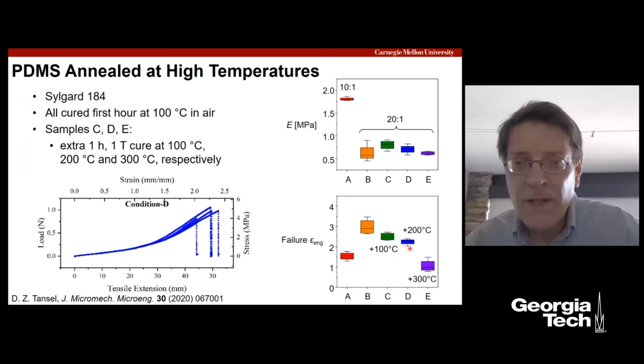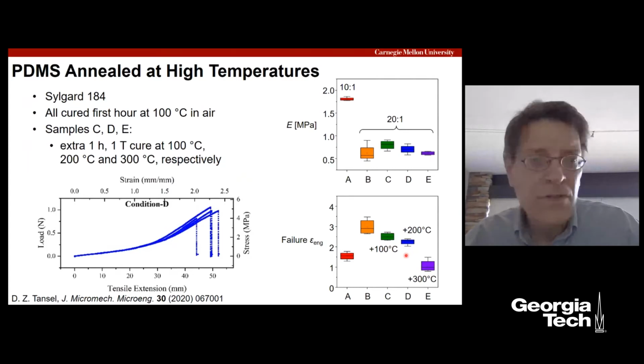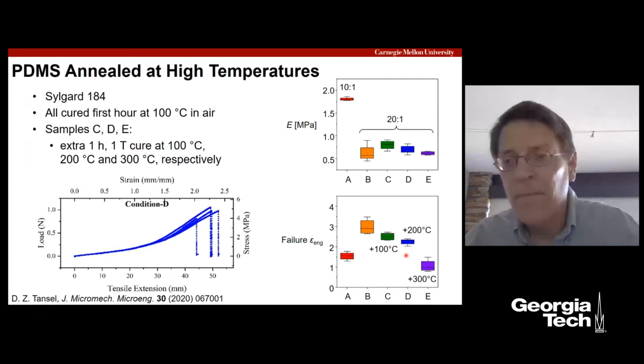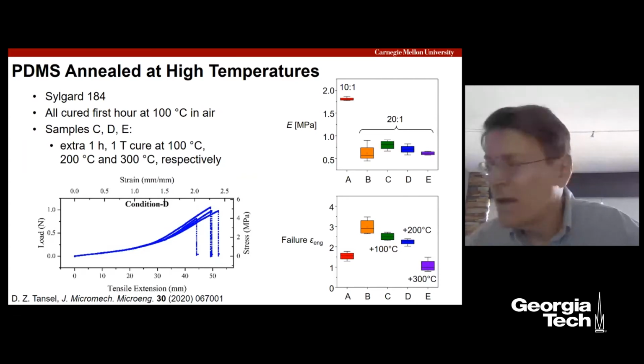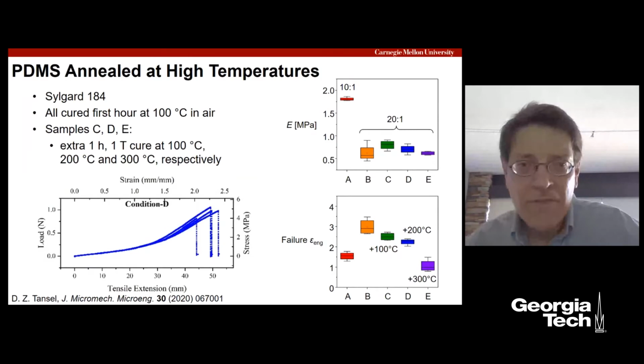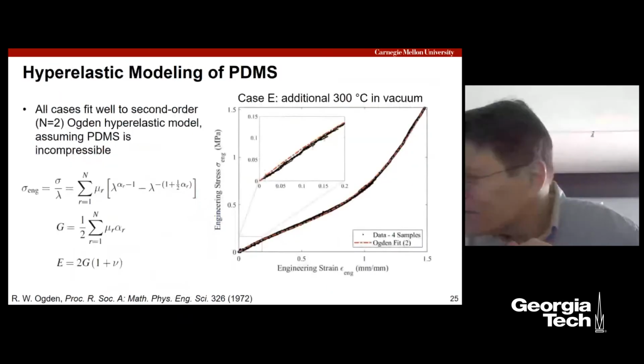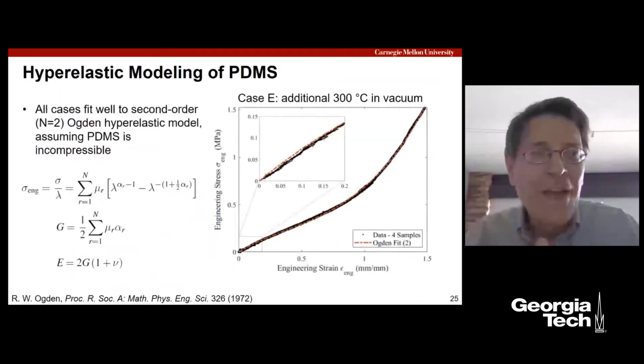However, ultimately, I'll just cut to the chase. I think we're settling on this 200 degrees C curing, and that's because we think we can get reasonable silver sintering. So we have to balance our PDMS and our silver sintering appropriately. I'm going to have to speed up, I think, because I realize it's 9:40.